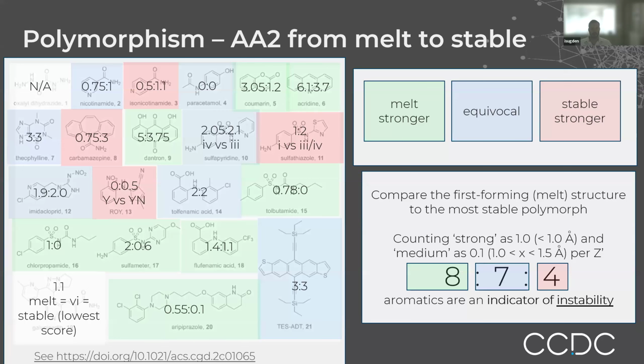Again, if we take a subset of structures where we have polymorphs derived from the melt, which are likely to be the kinetic forms and less stable, and then also a stable polymorph, and we apply the same aromatics analyzer to them, we can see that there are several where there are stronger aromatic interactions from the melt. There are a few where there's essentially the same interaction, and then there are only 4 with the more stable polymorph having stronger aromatic interactions. So in this way, aromatic interactions could be an indicator of instability, in fact.